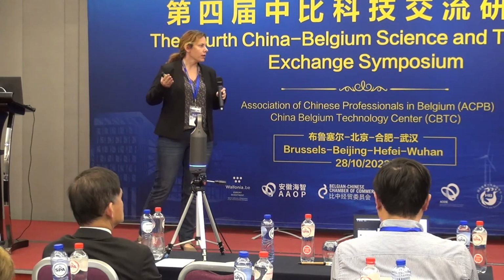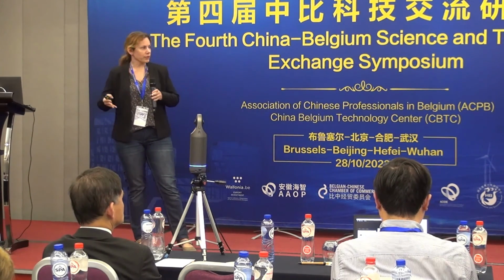Okay, so how do we actually create inorganic polymers? We basically take the amorphous precursor and an alkaline activator, which can be hydroxide or silicate. We mix it and we end up with an inorganic polymer paste, and this paste can be pressed, casted, 3D printed, or foamed. It can be cured at room temperature, it can be cured hydrothermally, so in a big autoclave, it can be even fired, depending on the application that you want to use it for.